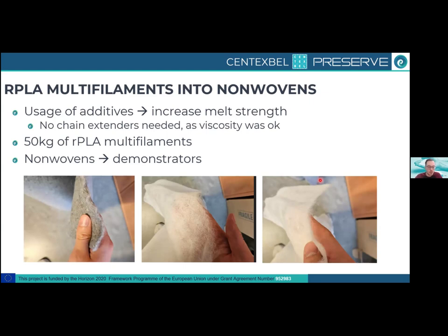into some non-wovens. You can see here 3 pictures on the bottom where we made 3 different types of non-woven. On the left side, we have made this together with denim fibers, so recycled denim fibers from the company Denim X, which is a thick non-woven which will be made into the carrier box. And then the 2 on the right are actually 2 different ones with 2 different thicknesses that are just pure